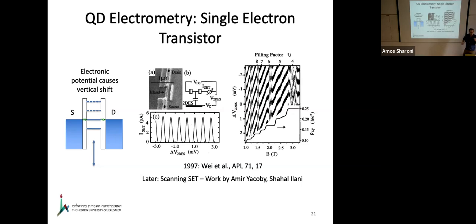This has been refined again by Amir Yacoby and then by Shahal Ilani as a scanning SET system, which is basically an extremely sensitive electrometer to anything that you can bring close by. And I want to point out the distances here. Typically, a quantum Hall system is 50 to 100 nanometers deep. That means that this device, which is patterned at the top, is 50 to 100 nanometers from the target system.